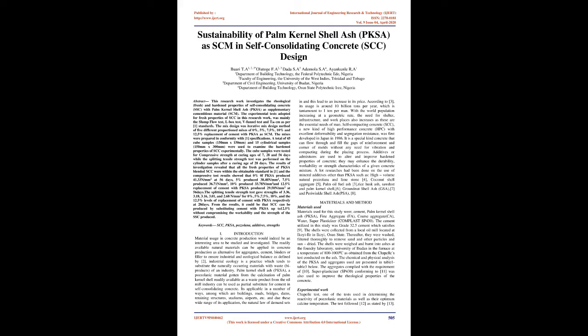56 days. The splitting tensile strength test gave strengths of 3.36, 3.18, 3.16, 3.01, and 2.68 N/mm2 for 0%, 5%, 7.5%, 10%, and the 12.5% levels of replacement of cement with PKSA respectively at 28 days. From the results, it could be seen that SCC can be produced by substituting cement with PKSA up to 12.5% without compromising the workability and the strength of the SCC produced. Keywords: SCC, PKSA, pozzolana, additives, strengths.